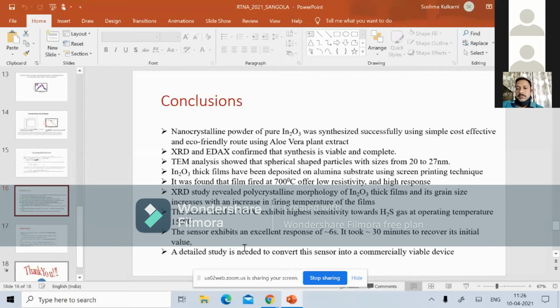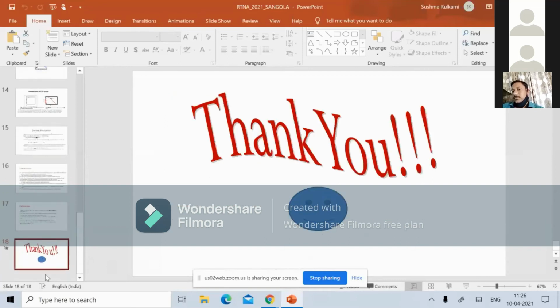The sensor exhibits an excellent response of 6 seconds, but it took 30 minutes to recover its initial value, and a detailed study is needed to convert this sensor into a commercially viable device. And in this case, the thickness I have measured using the profilometer. The thickness varies between 16 micrometer to 18 micrometer. And these are my references. And thank you for your kind attention.